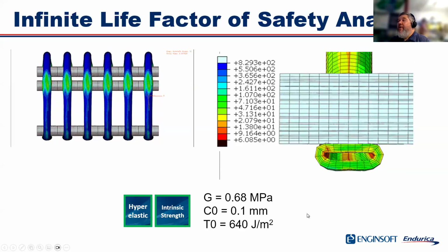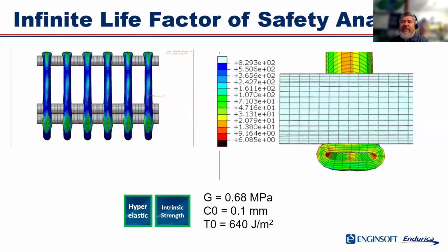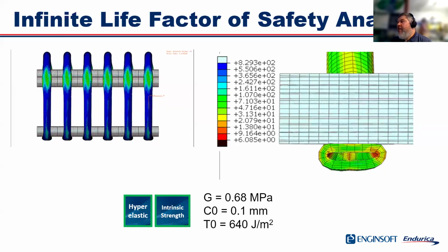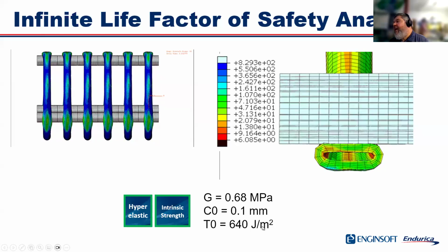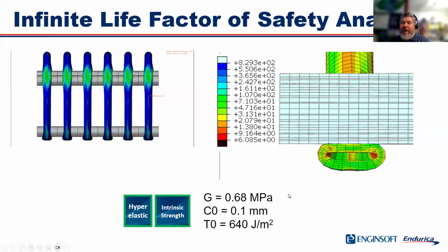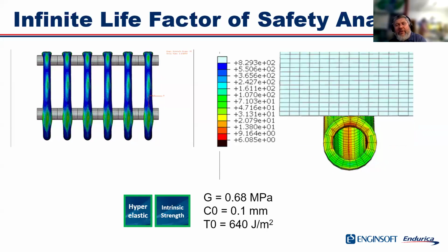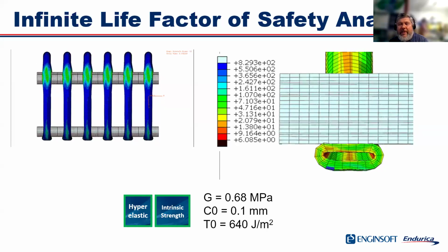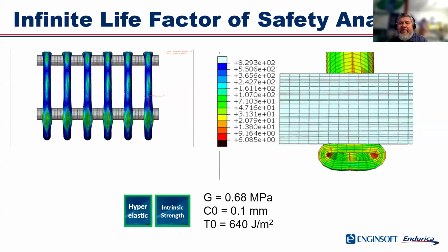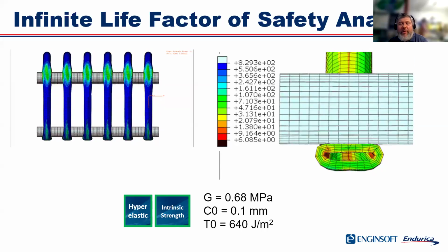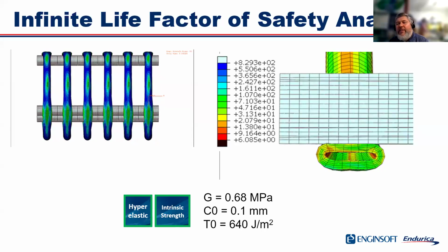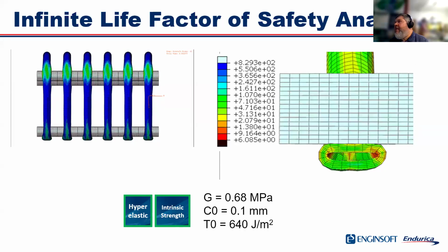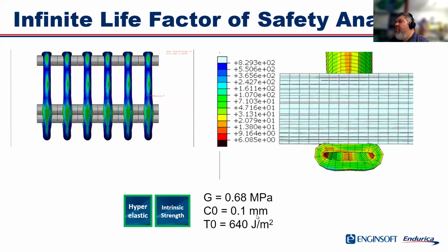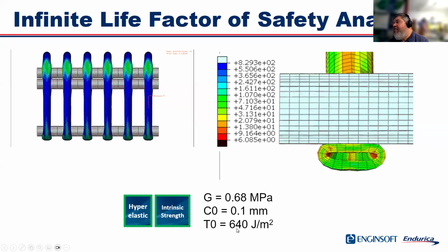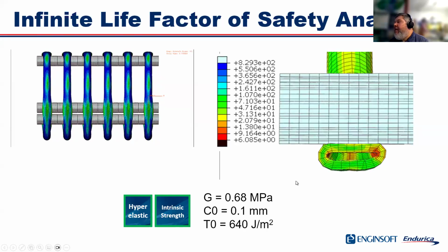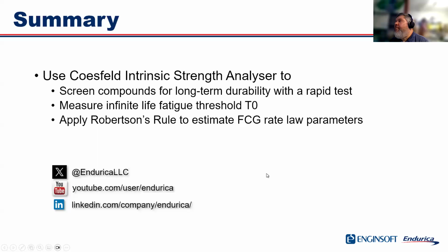But again, the beauty of this characterization is it's very simple. It's just a single test to get me my threshold value. When I use the infinite life method, I don't need to worry about rate or temperature dependencies. We would worry about all of that in a safe life analysis, but for these infinite life analyses, we just need to make sure we're below T naught, which itself does not depend on temperature or rate.